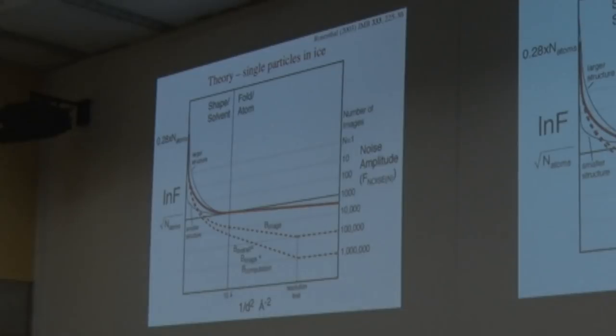At lower resolution, all the atoms in the structure are essentially in the same place. Even if it's a ribosome, they're in the same place to within a couple hundred angstroms. So they all scatter coherently, and the structure factor is equal to the number of atoms, with a bit of a solvent correction. And then at high resolution, you can think of the atoms as being random.